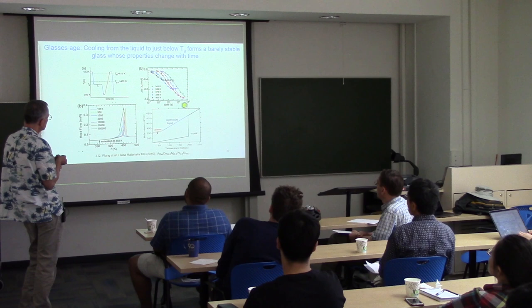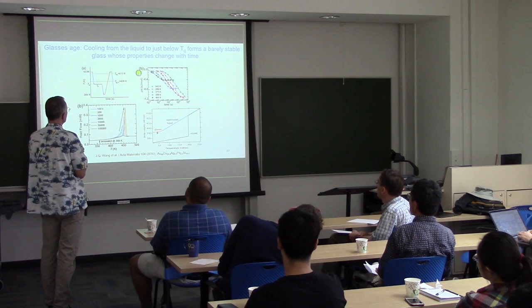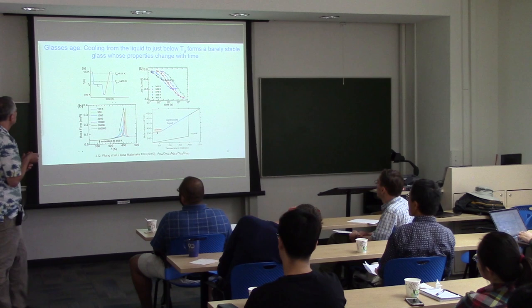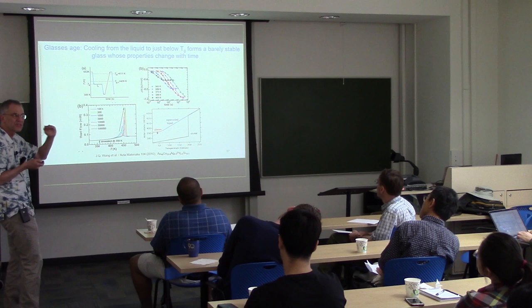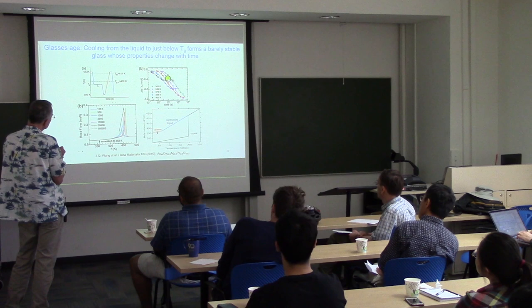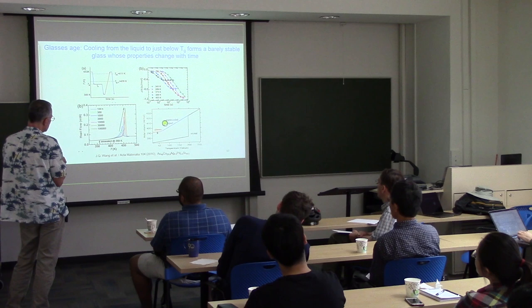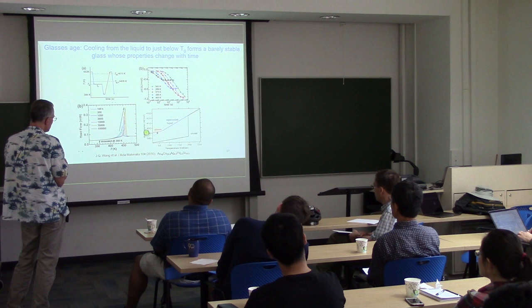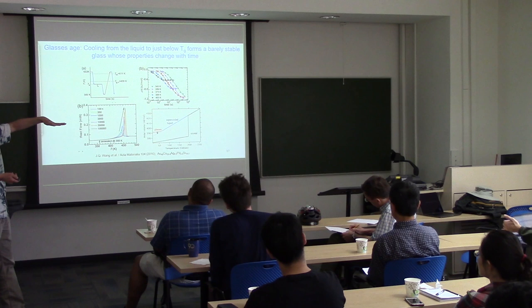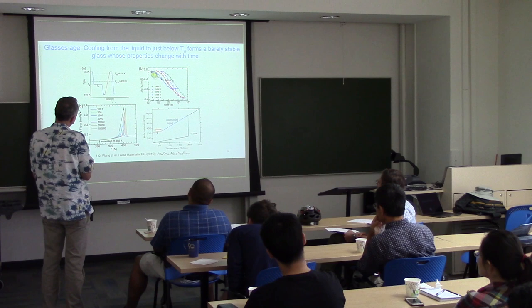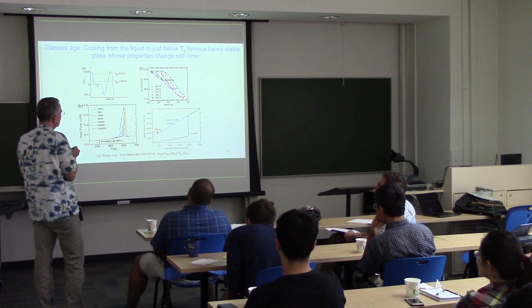Okay, so let's just look at the black curve to start with. Okay, so this was a system that was held 30 degrees below TG. And as it's held for a millisecond, up to a second, up to 10 seconds, the longer you hold it, the more the enthalpy drops, and then the enthalpy plateaus, okay? And that's because at this point, it's reached the enthalpy of the supercooled liquid. So if you want to look at that visually, think about this plot down here, and erase molar volume and write enthalpy, okay? And then what we're watching is the process of going down in enthalpy from one of the glass lines to the supercooled liquid line. We get to the supercooled liquid and we stay there, unless the system figures out how to nucleate crystals. Okay, so this is, in my language, the process of a glass aging into a supercooled liquid, because now it's in a metastable equilibrium state.